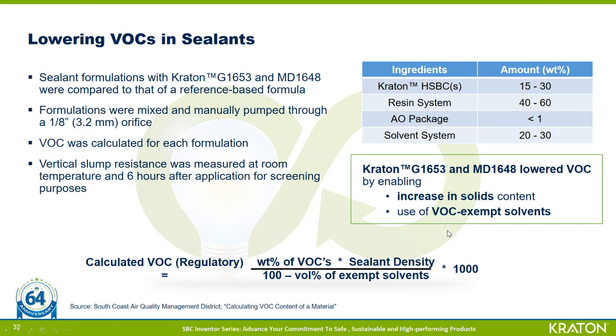So on our lab study, we found that Kraton products, such as G1653 and MD1648, allowed lower VOC content when we compared them to a reference sample by enabling an increase in solids content and the ability to incorporate the VOC exempt solvents.